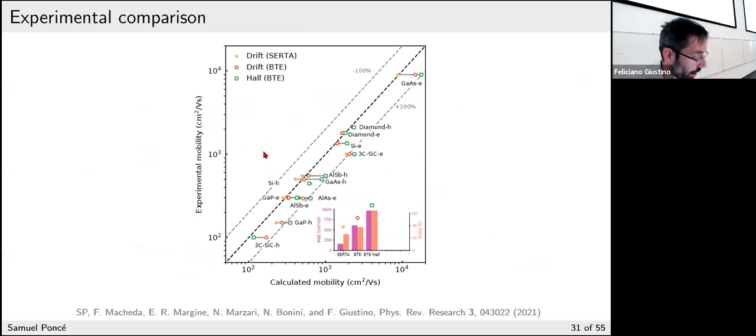Okay, so you can see indeed that you have sort of an overestimation. Maybe I shouldn't say that, but basically there are a few materials that are quite strongly overestimated, but actually those experiments are from the 70s, and I couldn't find any new experiment. And it seems like experimentalists don't want to do boring materials. But I do think that a few of them might get closer if you do more recent experiments. And indeed, for the more well-studied materials like silicon and diamond, you overestimate much less, right? So that's the first thing I can mention: if you compare to recent experiments done on really pristine, intrinsically doped samples and so on, you can expect a closer agreement, but you do overestimate.